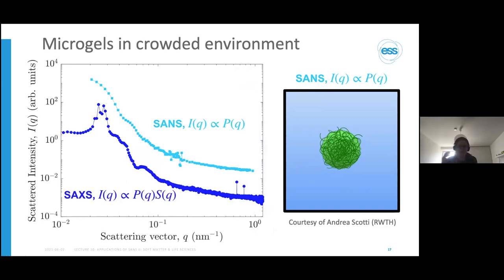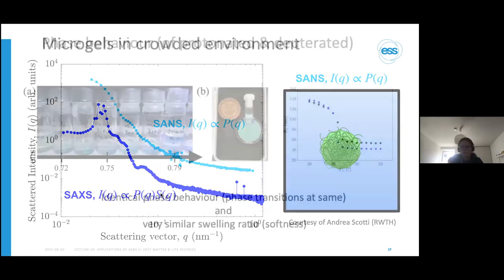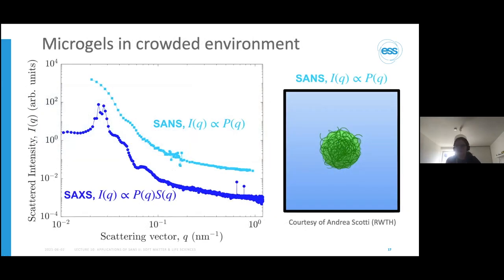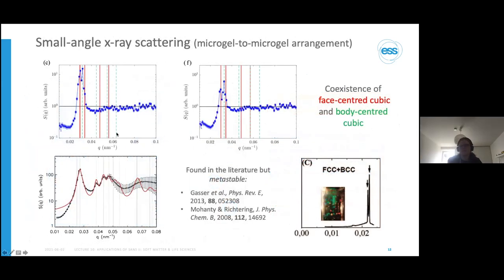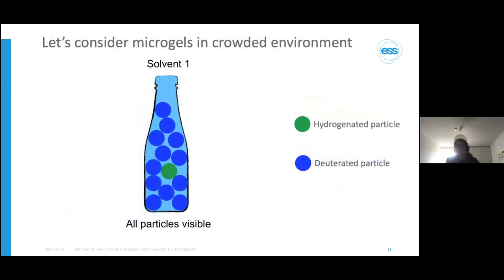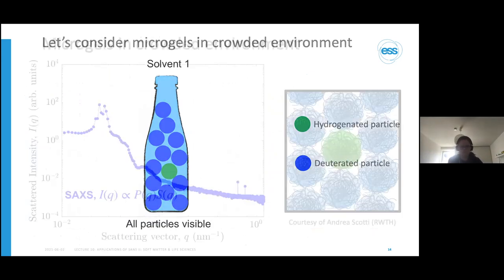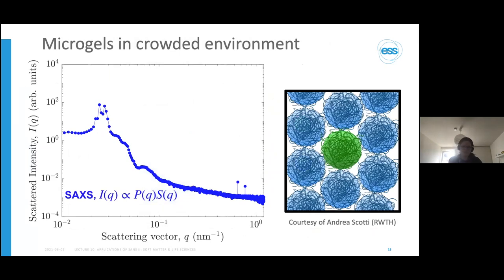From one sample using X-rays and neutrons, we get both pieces of information. By dividing the SAXS data—I(Q) proportional to P(Q)·S(Q)—by the SANS data—I(Q) proportional to just P(Q)—we can isolate the structure factor S(Q). This is a really elegant use of combining X-rays and neutrons to get more information from your sample, and I'd highly recommend trying this approach if you have these type of systems.